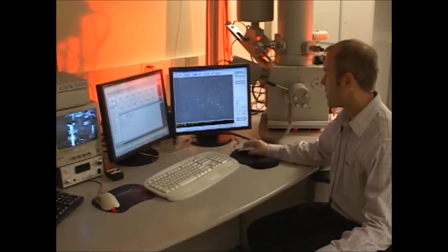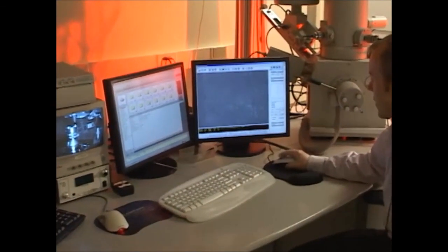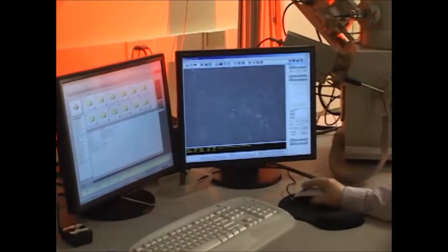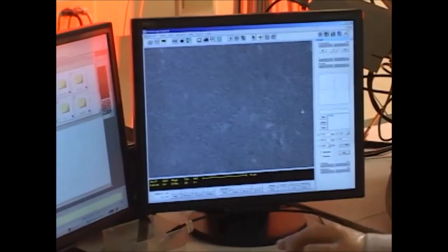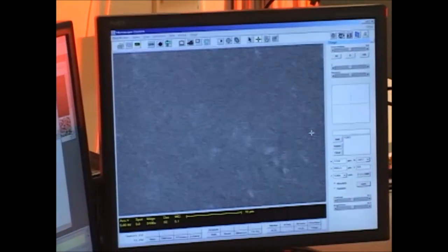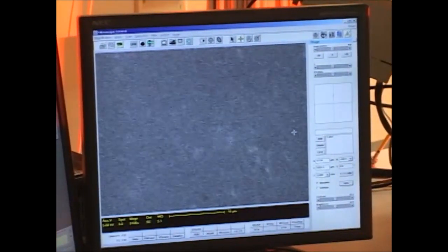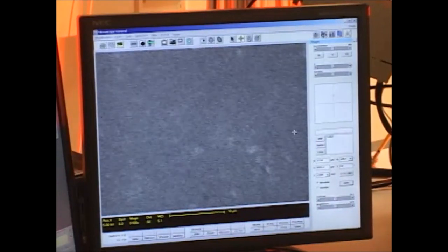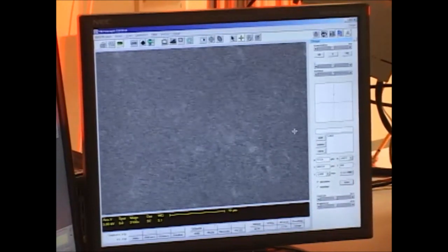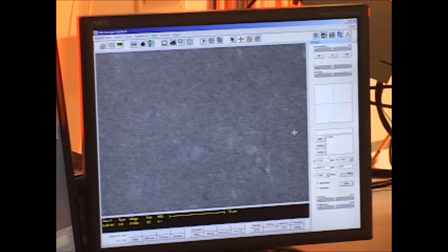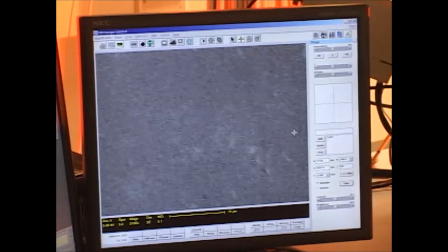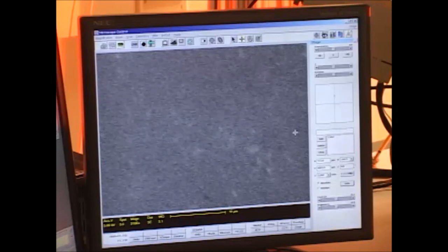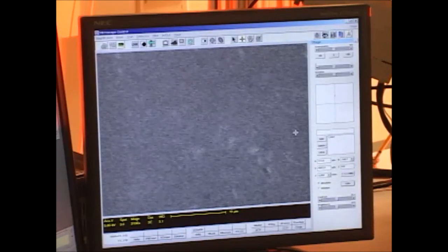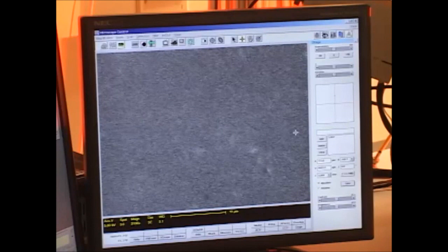We're at the final working distance, so again I'll focus, and I can't see very clearly because the beam conditions haven't been optimized yet. Even though the sample's in focus, if the beam isn't perfectly round, we'll get a distorted image, and that hurts our resolution quite a bit. When the beam is optimized, we should be able to resolve down to about 10 nanometers, 10 nanometer size structures on the surface of the sample.